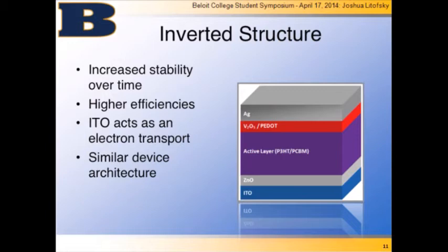One thing is that this has increased stability in air over time. A problem with the conventional cells is that they decay pretty rapidly when you expose them to air. That's why all the production is done in the glove box. When I was testing some of the conventional cells, we had our testing outside of the glove box, in the ambient air in the lab, and I could test it right out of the glove box. The glove box, by the way, is nitrogen rich.